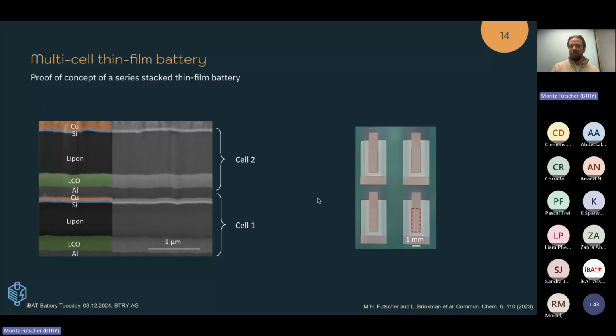On the right-hand side, you see a photograph of these cells. They are very tiny. So they are 1 by 3 millimeters in size. And you see that there are different contact designs, such that we can contact the bottom cell alone and also the top cell alone, but also we can contact them together. And on the left side, you see a cross-section SEM image of both of these cells stacked on top of each other. In this case, we now have LCO as a cathode. This is even an amorphous LCO cathode. This is not the best cathode at all, but this was really just for demonstrating the proof of concept.